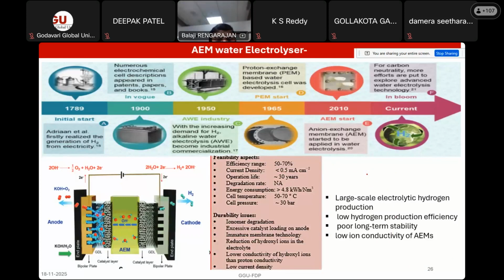This is a new technology which will also function similar to the PEM technology. But here the advantage is, again, you don't want to use alkali water. You can use only pure water, and then you can favor the gas evolution, hydrogen and oxygen gas evolution, in 2 different compartments. And this AEM membrane will also have a dual role of separating gases as well as allowing exchange of ions. So membrane as well as separator.